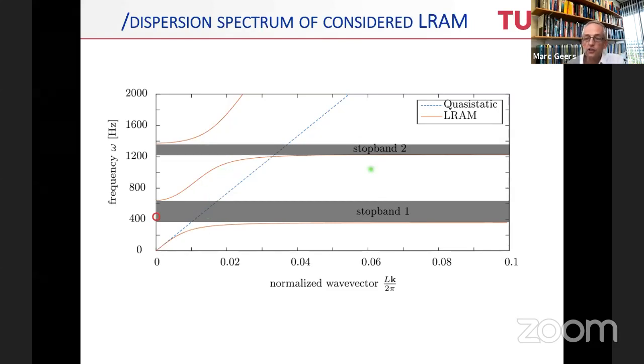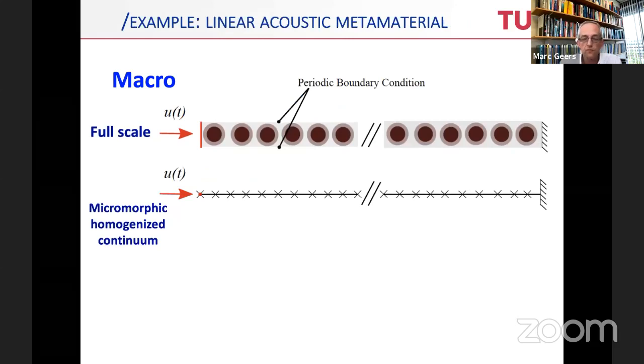What you can notice is that the effective continuum that we recover adequately picks up the two stop bands and the dispersion curves, the different branches like the acoustic branch which we see here, of this particular LRAM. So it's clear that it works, and it's an effective continuum that you can use to solve boundary value problems with. That makes it, of course, interesting. I'll show a few more examples. Here is the example of a whole array of these LRAM resonators. The full-scale model is solved here with direct numerical simulations, which means that we discretize everything. And we replace this by a continuum, which is almost a thin line. It's a 1D continuum if you replace it, in which the wave propagates from the left to the right.